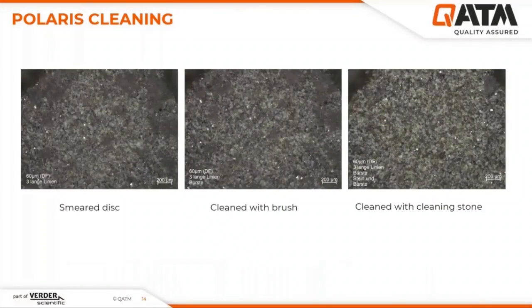Here you can see microscopic images of the surface of a grinding segment. In the left picture, you can see a disc with large parts clogged. After cleaning with a nylon brush, there is no real improvement. Only after you have used the cleaning stone will you see that almost the entire surface is free again. So the stone must be used as soon as you notice that the disc is clogged and no longer working properly.